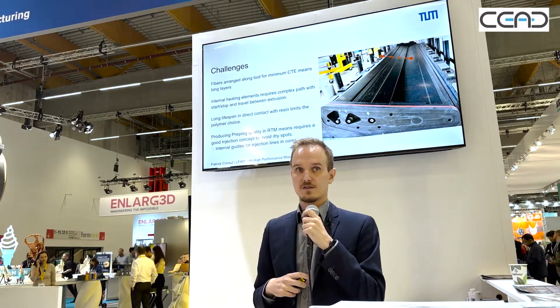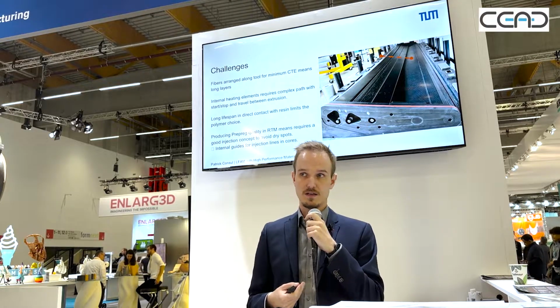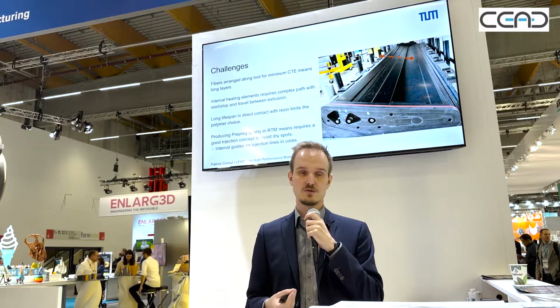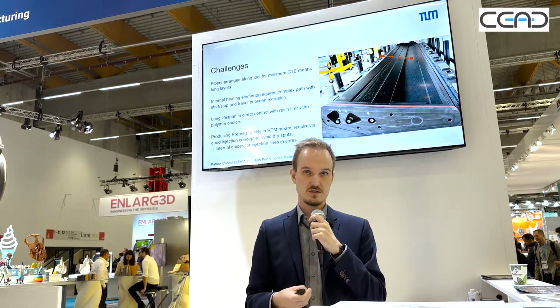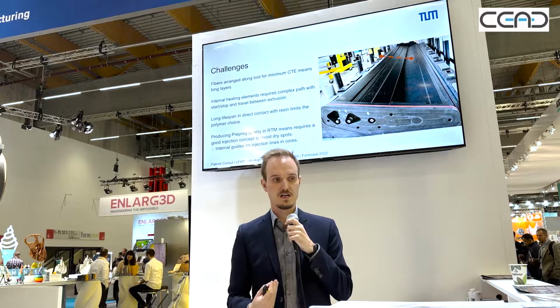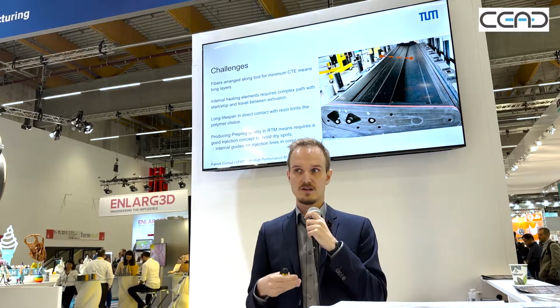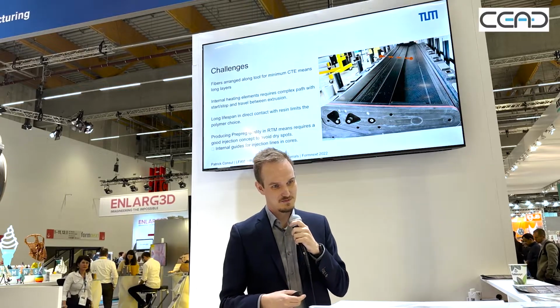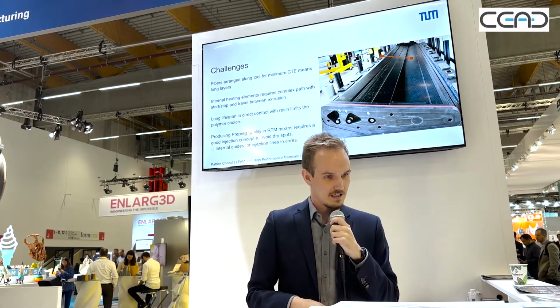So many of you probably are thinking that you could print this with PEI and it's easier than PEEK. And that's probably right. The problem is that PEI is actually soluble in the resin that you use for RTM in aerospace industry. So if you have direct contact with the resin, your part will permanently become part of your mold, which means you'll have to replace it quite often.